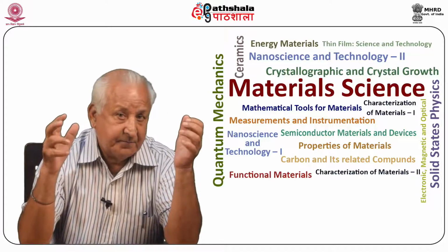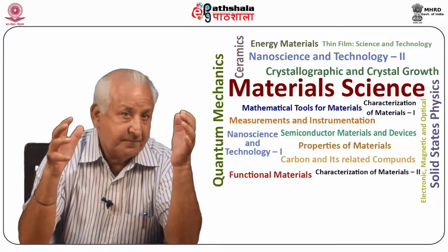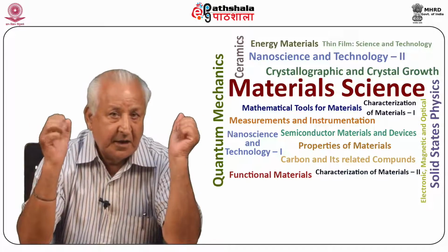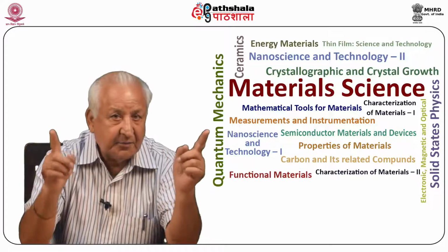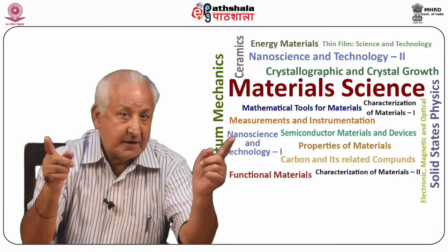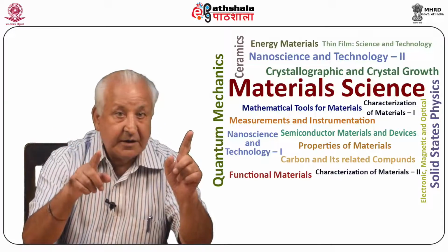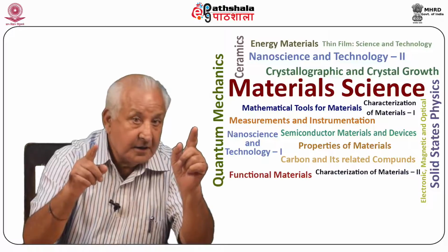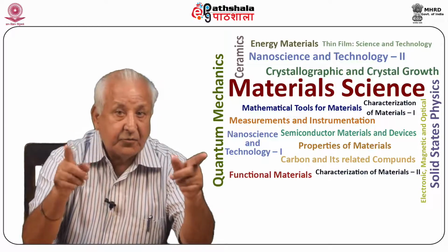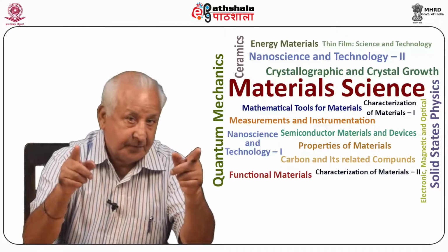If the sphere, known as Ewald sphere, does not pass through any points, it will suggest that the particular wavelength in question will not get diffracted by the crystal in that orientation, and readjustment of orientation will have to be carried out for diffraction to occur.